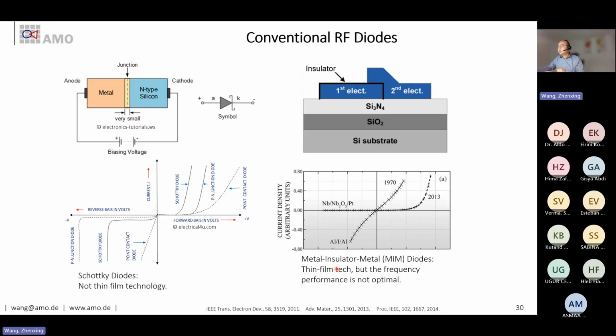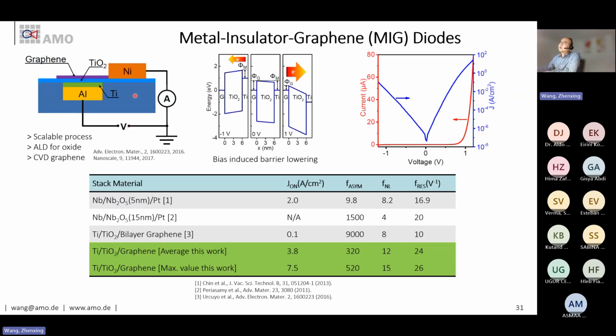For metal insulator metal diodes, it's a thin film technology, meaning you can do it on whatever substrate you want, but the frequency performance is not optimal, because you see this is one electrode, second electrode, and there is a direct capacitance between these two electrodes, which limits the RC, and then you don't have very high frequency response. So what we propose here is graphene. I actually mentioned it before, metal insulator graphene diodes. So basically the titanium or aluminum is the metal, one electrode, and then you have titanium oxide here and graphene on top. And then you have the nickel contact to graphene.